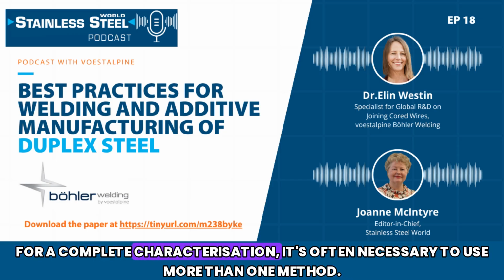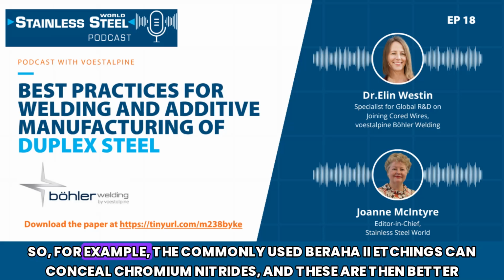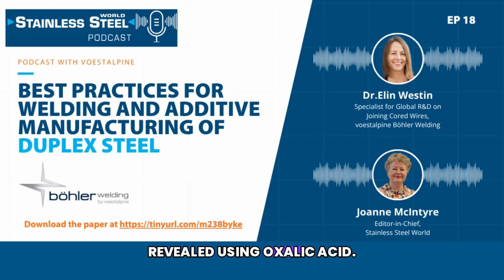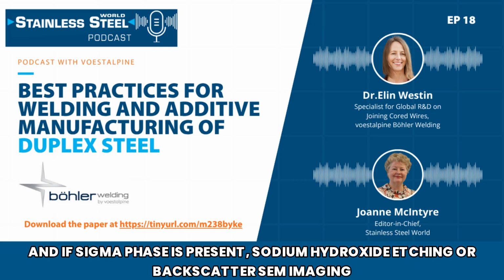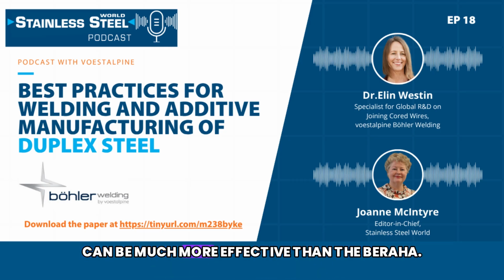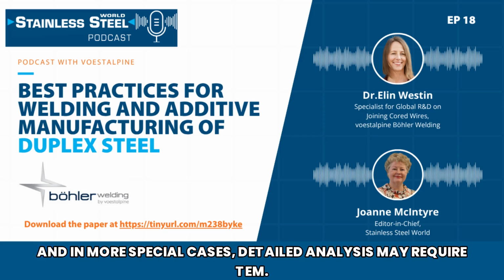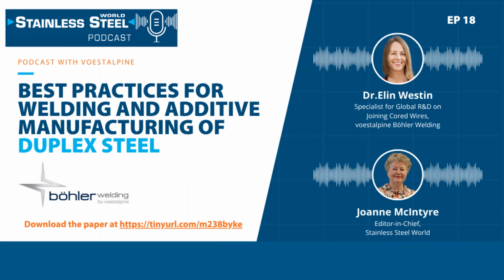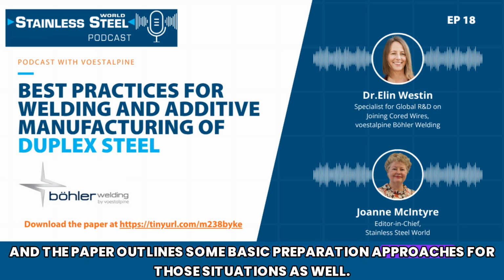For a complete characterization, it's often necessary to use more than one method. So, for example, the commonly used Beraha II etchants can conceal chromium nitrides, and these are then better revealed using oxalic acid. And if sigma phase is present, sodium hydroxide etching or backscatter SEM imaging can be much more effective than the Beraha. And in more special cases, detail analysis may require TEM, and the paper outlines some basic preparation approaches for those situations as well.